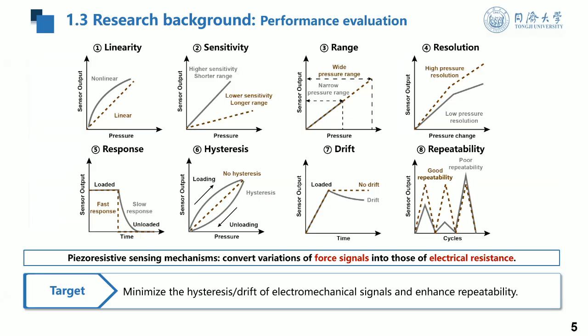But most of the sensing materials are made of composites, such as nanocomposites. We can use nanofillers such as carbon nanotubes, graphene, MXene, and so on, to improve the conductivity and also control the stiffness of the nanocomposites. But polymeric materials have inherent viscoelasticity, which makes the sensor have time delay, leads to hysteresis in the signal response, or makes the signals drift.